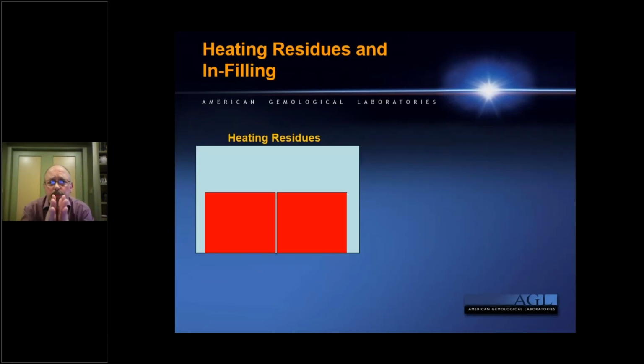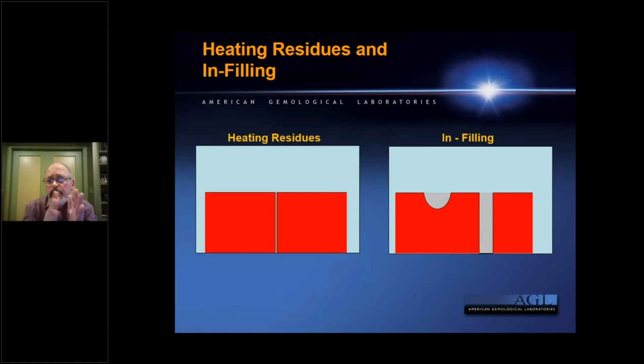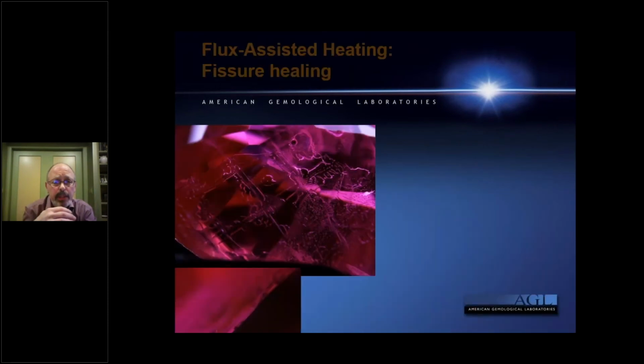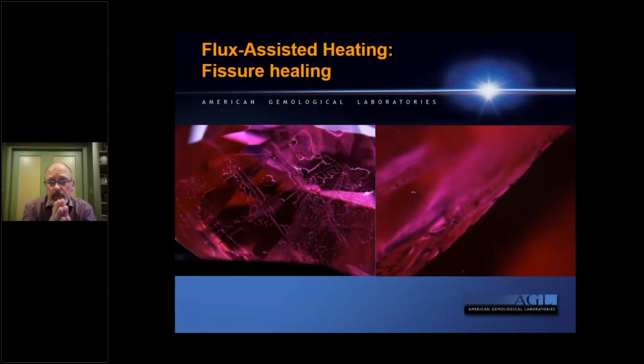So now, up till now, we've been talking all about this healing of fissures and heating residues. This is, again, the healing of very fine fissures where the opening is very fine. Next, I want to talk about the infilling. Fluxing agents also have the ability to fill in areas on the surface. This can be cavities which are present at the surface. These can also be broad fractures, where you have very little healing take place, and essentially what you have is just the fluxing agents or the vitreous melt infilling these materials. And so I want to show you a little bit of what that looks like. This is a broad fracture which has infilling.